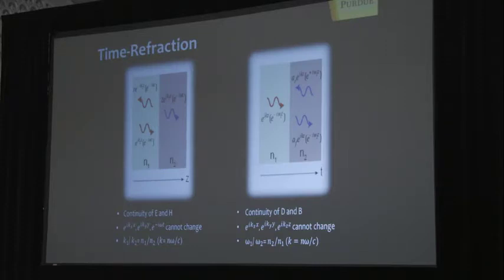So you could also look at this like conventional refraction. You could treat it as a space refraction. And what we are talking about is time refraction. In conventional case, when light goes through the interface between two materials with N1 and N2, of course frequency should be conserved, and the momentum changes in accord with the dispersion relation. If I now change refractive index in the time domain, wave vector should be conserved, but frequency changes in accord with the dispersion relation. So it's basically space and time complementary, we know this, and it kind of makes it cool and broadens the scope of use of these metasurfaces.